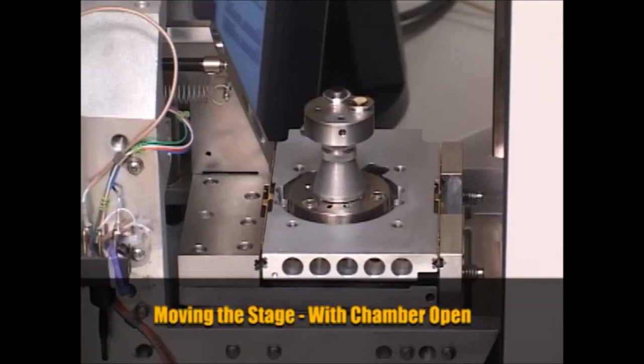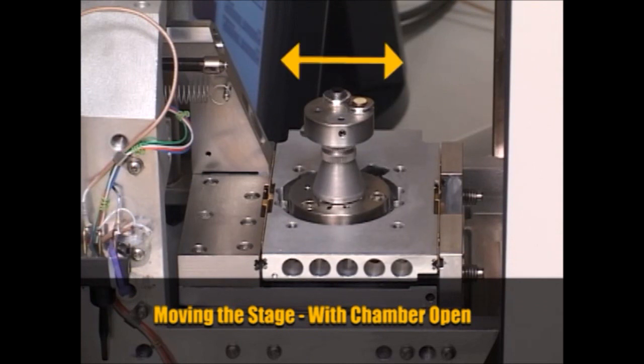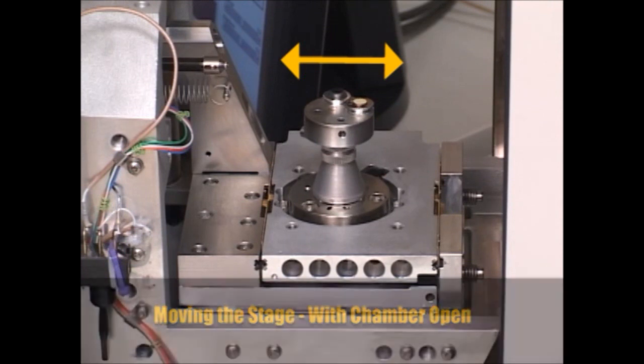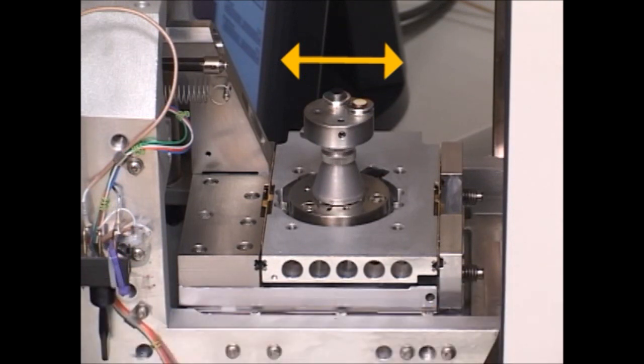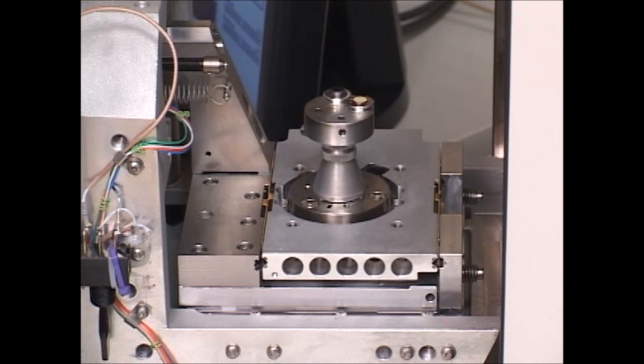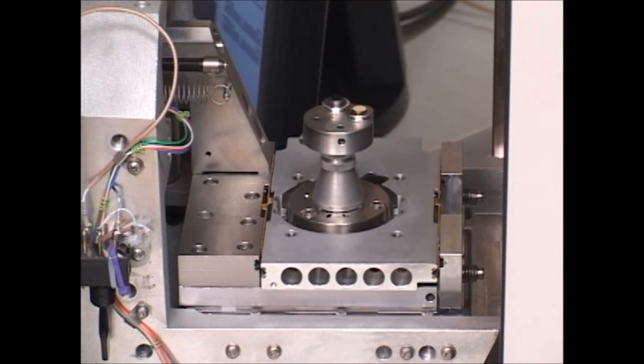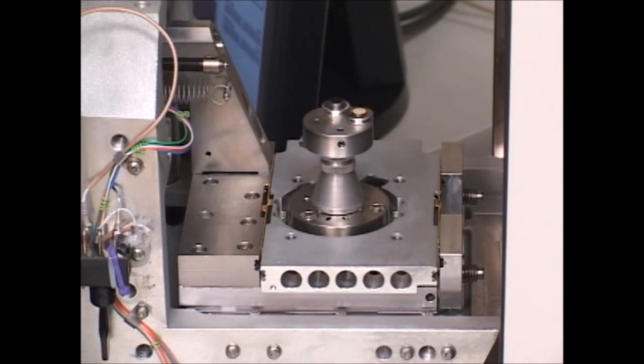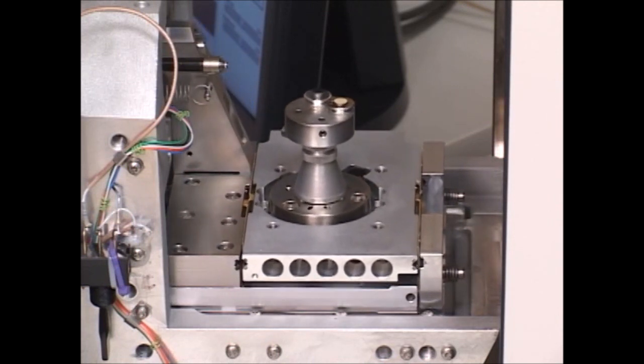When the stage track mode is on, I can go up in the X direction, and we're moving about this fast when we're using that donut tool to drive around. Here's a little bit larger step in the Y direction, and then moving from the gold to the tin sample, we dropped the stage down and then we moved it laterally like this in both the X and the Y.